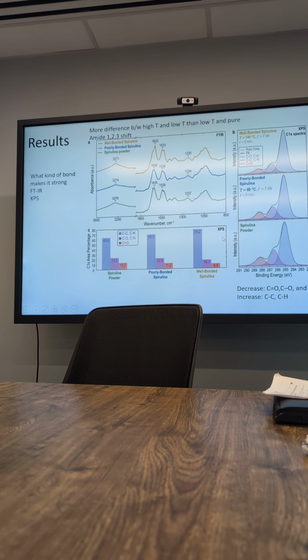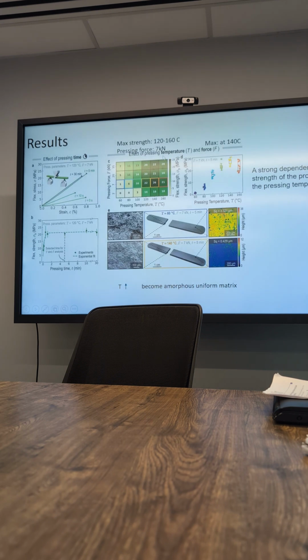So from this we can tell that during the pressing, more beta sheet is formed, and because I already said beta sheet has more stiffness, that explains why at high temperature their mechanical properties are so much better. So these blue ones, they call the poorly bonded material because they are just at 60 degrees, and these ones are 140 degrees, and from above we know when temperature is 140 degrees, the strength is the best.